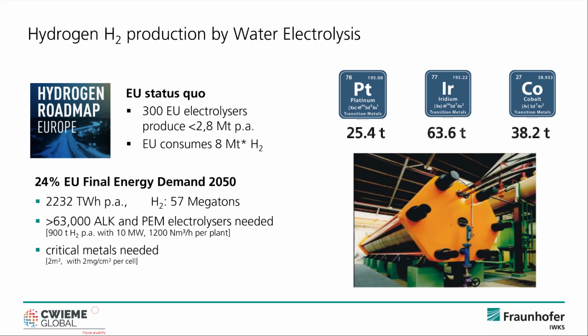For the catalysts, or for the electrodes of these water electrolyzers, platinum, iridium, and cobalt are used. And if you consider these numbers, the 60,000 electrolyzers require 25 tons of platinum, 60 tons of iridium, and about 40 tons of cobalt. And everybody knows these are critical elements as they are cost intensive, but they are also under high competition with other applications. Cobalt, for instance, is a major ingredient to the active materials in lithium-ion batteries. So there is a competition, and the market for these is under a certain stress.